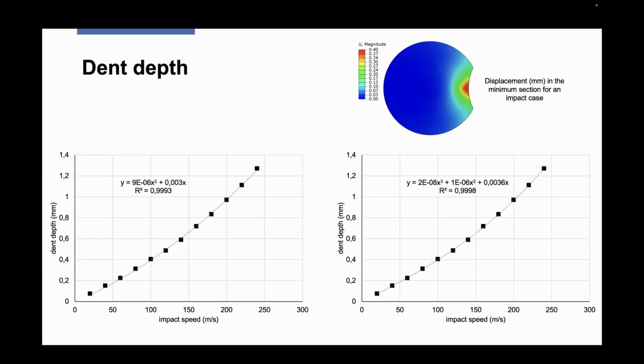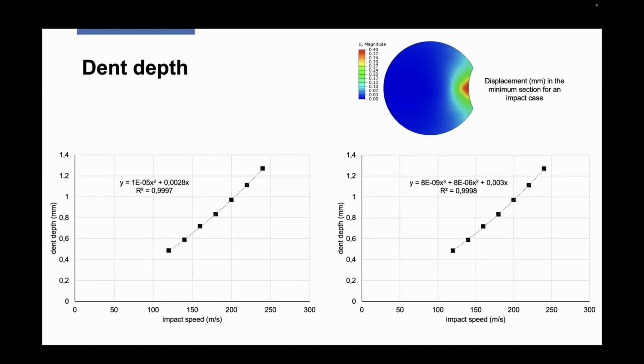We studied the influence of the impact speed on the dent depth, and as we can see, the trend can be parabolic or cubic. The R square values are very, very close to 1. But if we neglect the small impact speeds, you can see that the parabolic trend is good. We have only a very, very small variation in R square.